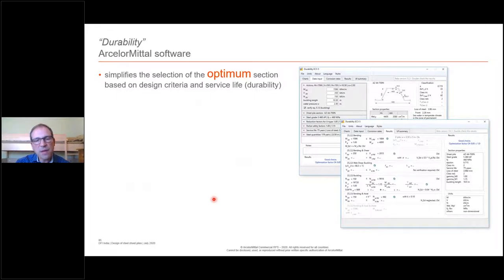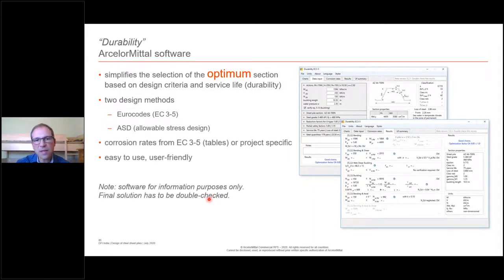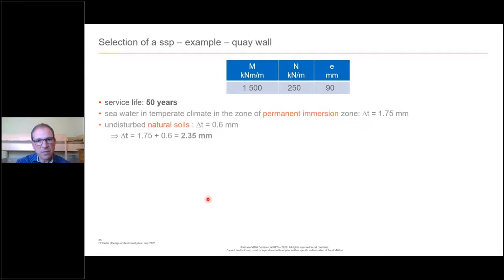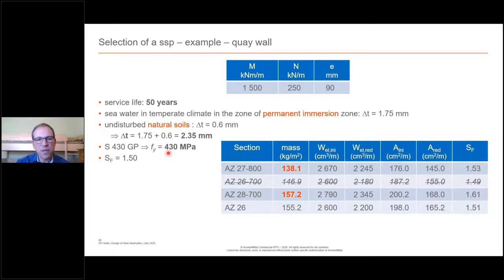We also have software that can simplify this task, quite handy, also based on Eurocodes and allowable stresses. It also has the database for the corrosion rate from Eurocode 3-5, so the table that I showed to you. And a simple example, again, with the permanent immersion zone and the natural soils, where you lose overall 2.35 millimeters, and then you take a steel grade with a yield strength of 430 MPa, you go into the catalogs and then you choose the ones that might be sufficient, where you have a sufficient safety factor. Depending on the pile that you choose, in this new range which is 800 millimeters wide, there is a big difference in the mass, from 138 up to 157, so approximately 15% that you can save by using the most adequate sheet